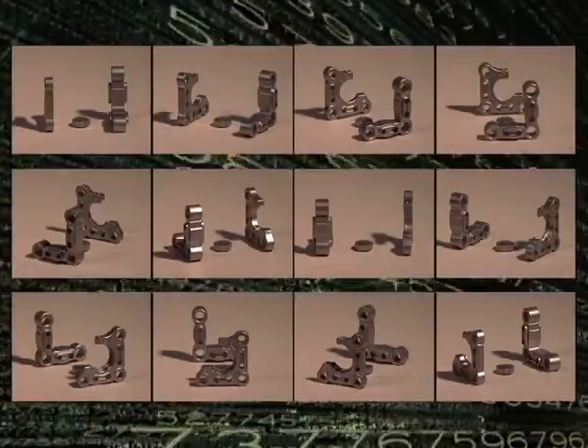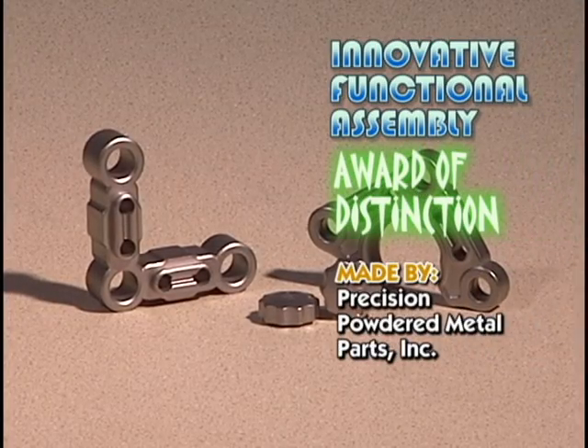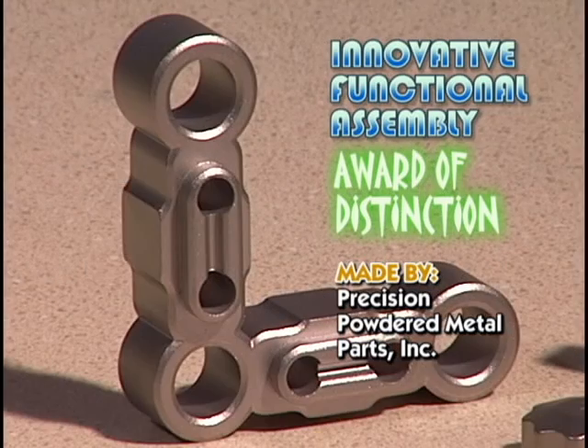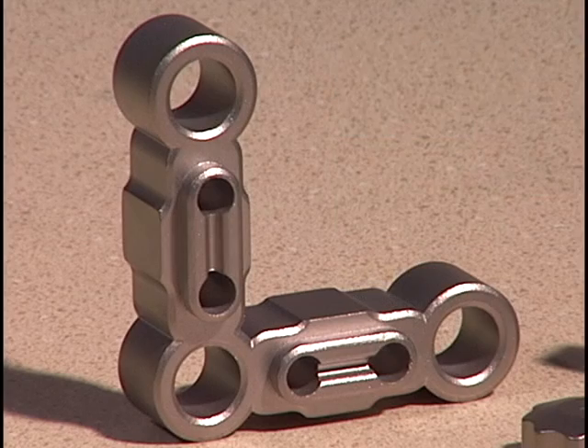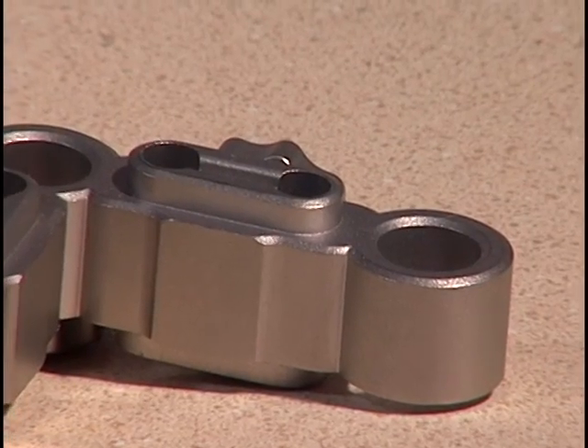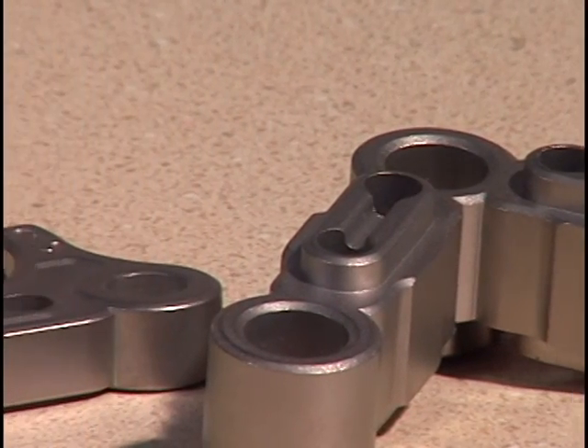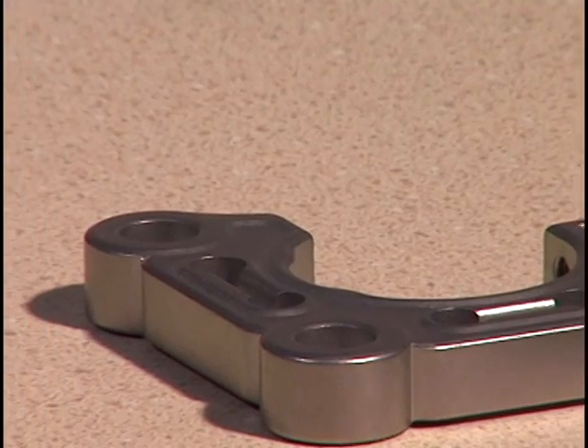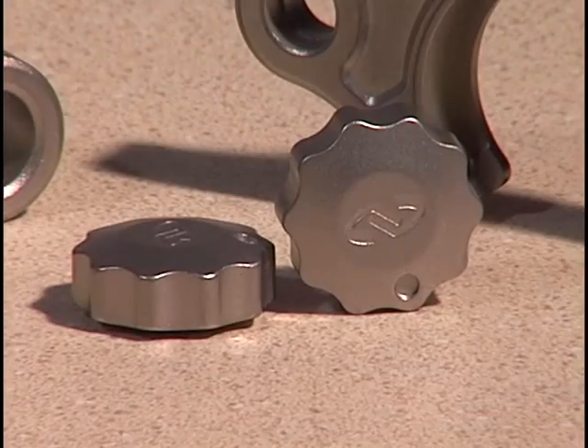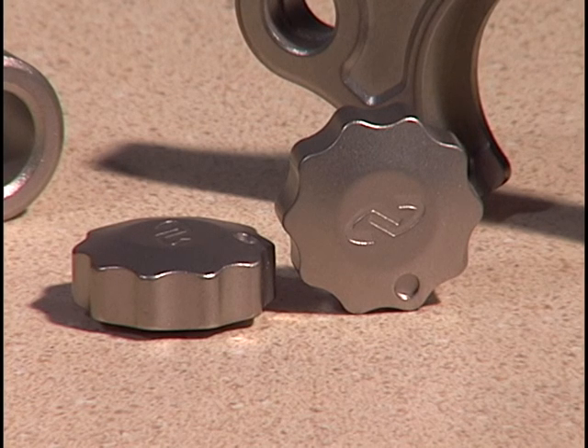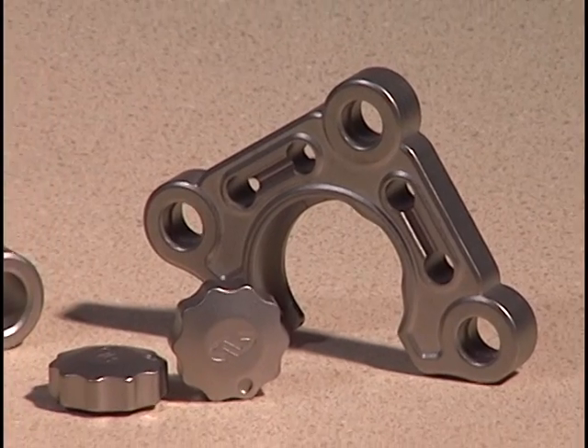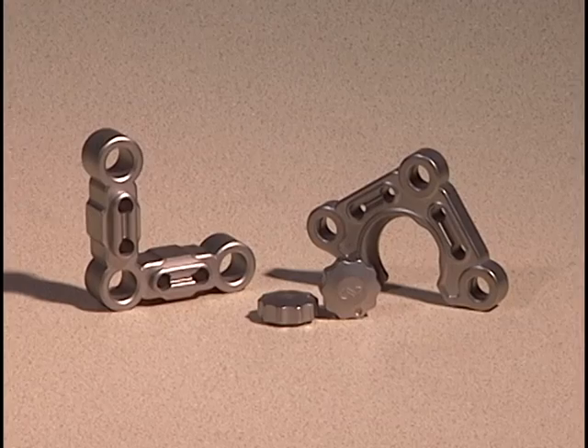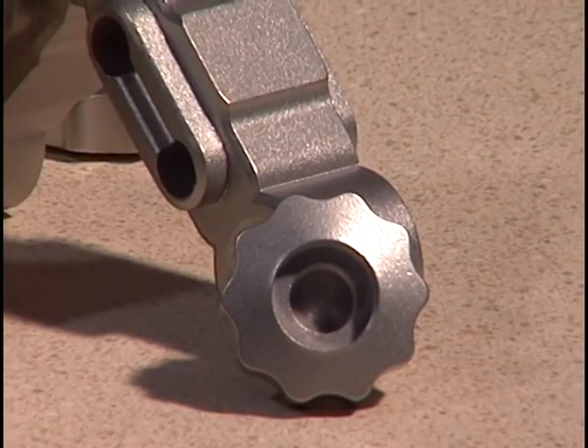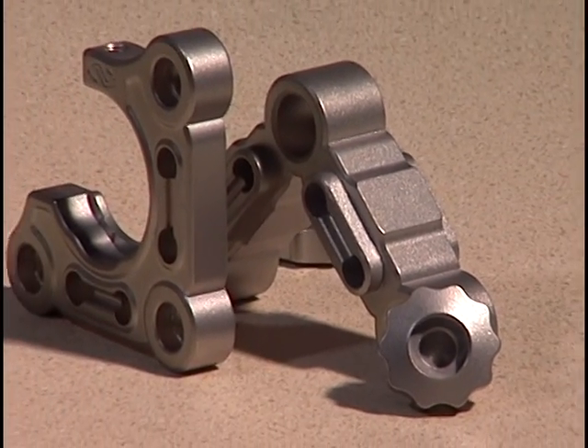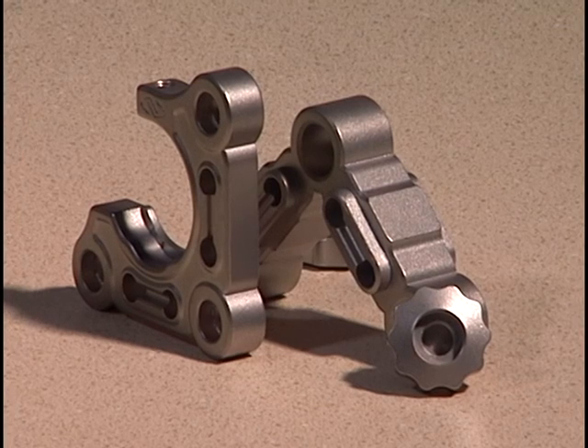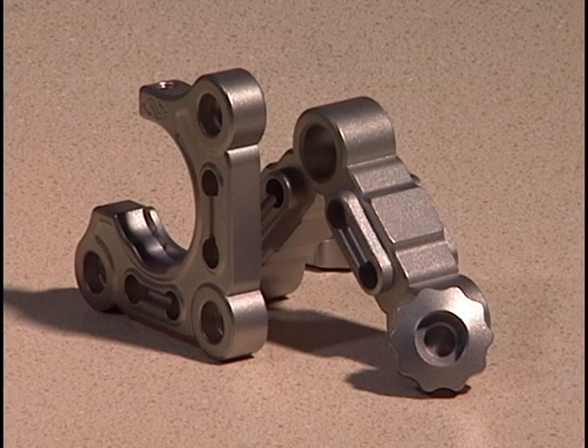This kinematic optical mount used in laboratory equipment has won an award of distinction in the Innovative Functional Assembly category. Made by Precision Powdered Metal Parts, Inc., the optical mount holds a mirror lens that directs and deflects a laser beam with 2 100-pitch thread adjustments. The 316L stainless steel part is fabricated to a density of 6.4 grams per cubic centimeter and has a yield strength of 25,000 psi. The patented PM assembly replaced a previously machined aluminum version, but with improved precision, aesthetic appearance, and minimal thermal expansion at room temperature. The complex part is subjected to deburring, drilling, tapping, and blasting with glass beads to enhance its appearance.